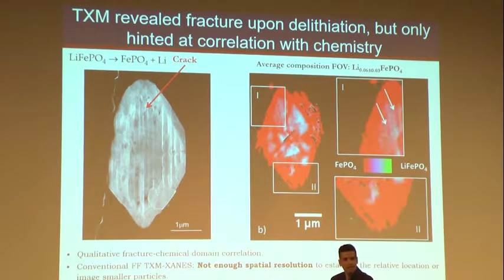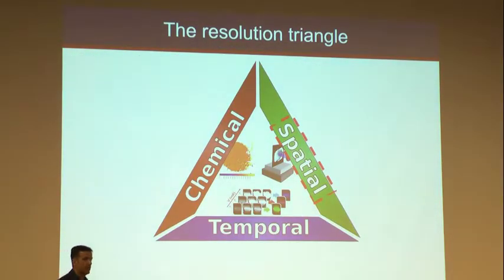This is where the spatial resolution was. We tried all sorts of tricks to try to put the images on top of each other. It was very hard to tell. And so this to us gave us reason to see what was out there to be able to increase the spatial resolution. It's also useful if you can look at smaller particles than this, because the vast majority of battery materials are actually more on the sub-micron size, and these are up to 4 microns in size. And so that's where development in spatial resolution were needed.